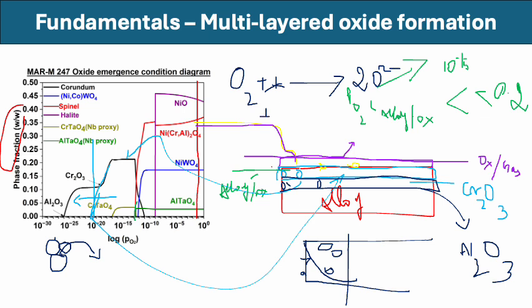Then it reductively adsorbs, which means there are 2 electrons also involved. Actually 4 electrons. So this is an electrochemical reaction that is happening on the surface, by which the oxygen dissociates and adsorbs reductively on an adsorption site, which is denoted by a star mark here. This is the FCC site in an 111 plane. So this is the first step.